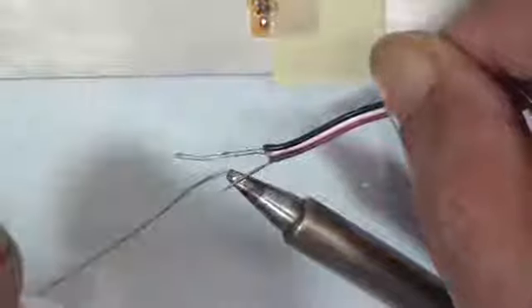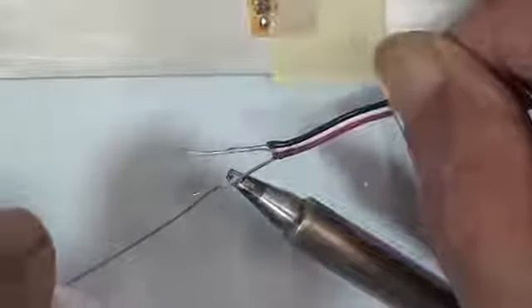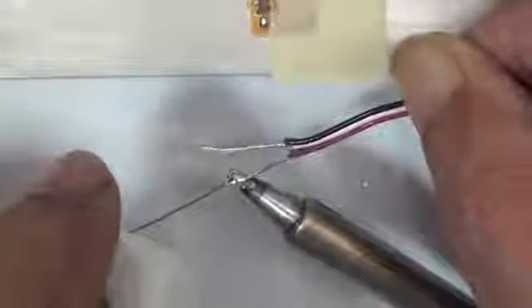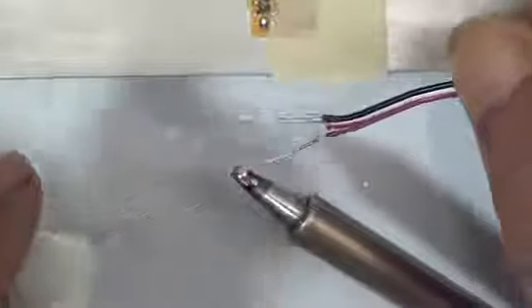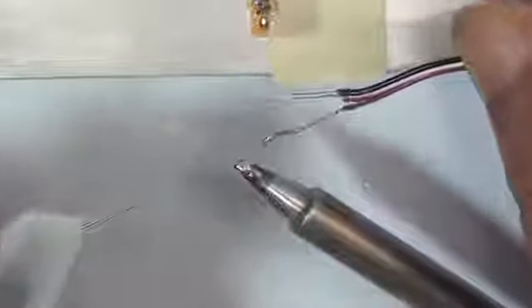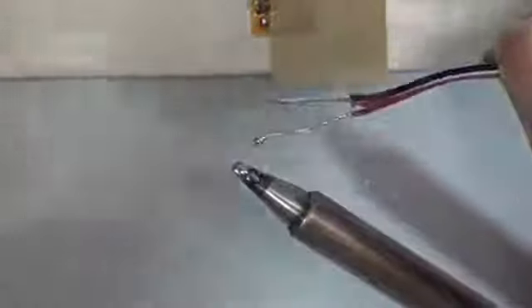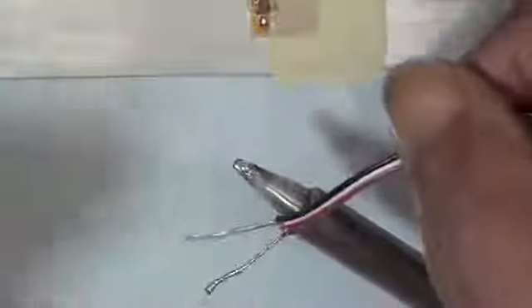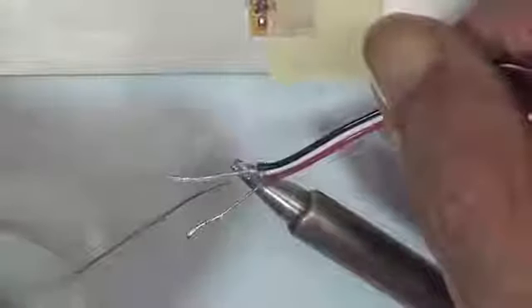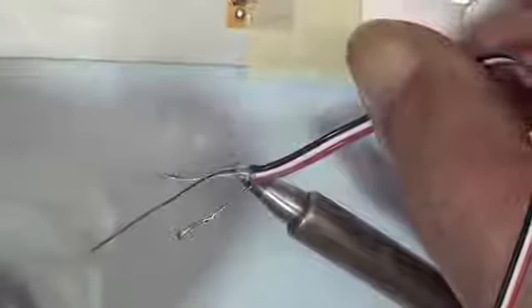A very common mistake in strain gauge work is to use a sharp pointed tip. Now that's going to apply a point heat source to the foil, and that foil that makes the strain gauge is extremely thin. It has no thermal mass. Therefore, the heat does not radiate out from that point. So you end up with a hot spot that the solder flows on and a cold spot around it that the solder does not flow, and you spend excessive time trying to get the solder on the tab.